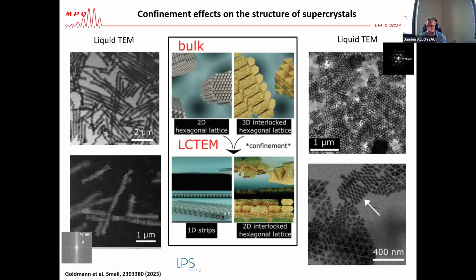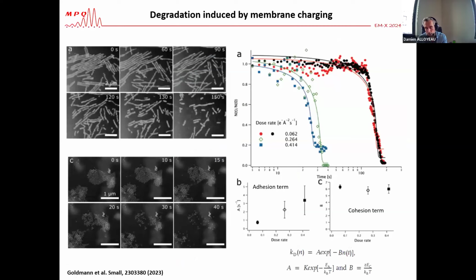So at the end, what we have in the liquid cell is nanocrystals with the same structure, the same lattice parameter, but with a much lower dimensionality. And at the end, my colleagues were very happy because they say that we now have the opportunity, by adding a membrane, to change the structure of our supercrystal. So it's a way to control the structure of supercrystals, but it's also crucially important to know that you don't necessarily always have the same result inside your liquid cell and at the bulk scale. And we wanted to understand why.